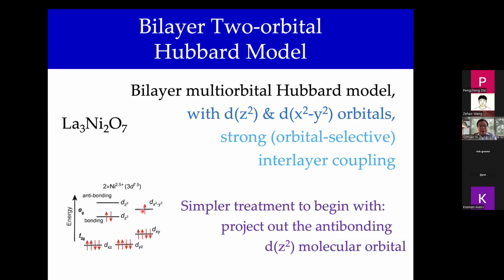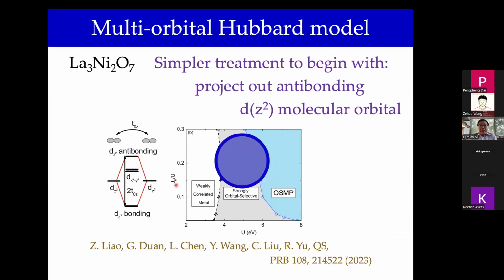So as I said, in the initial calculation we decided to throw away the anti-bonding orbital, but we keep the Hubbard interaction and the Hund's interaction, and studied this multi-orbital Hubbard model using some auxiliary particle representations, specifically this U(1) slave spin representation, and carried out the saddle point calculation. So this is the overall phase diagram that we determined. U is the Hubbard interaction, and the vertical axis is the ratio of the Hund's coupling to the Hubbard interaction.